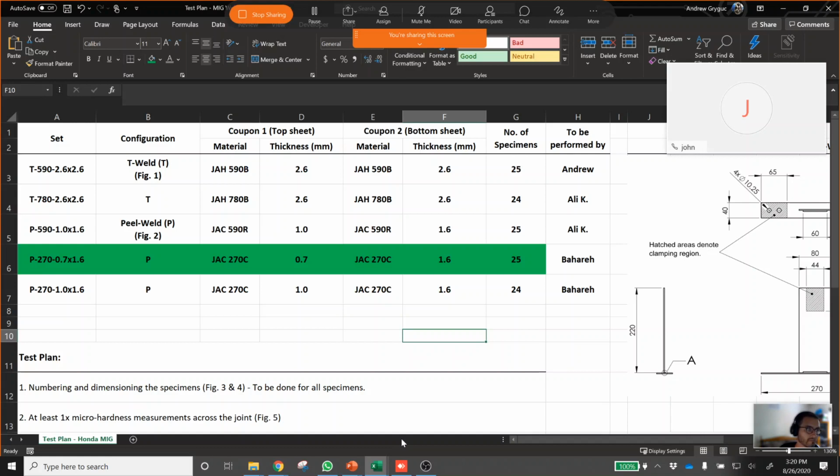Okay. So if the length of the weld is much longer, probably the weakest point may be the base material itself. Let me know when you do the 0.7 to 1.6, at least on that, since the weld material is stronger than the base material itself, we should be able to see the crack initiation on the base material. Understood.